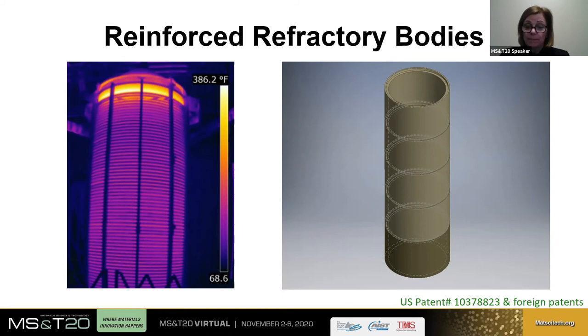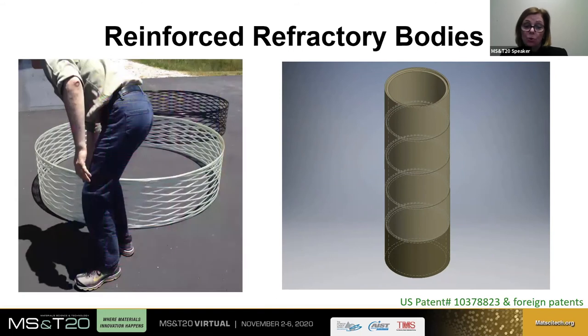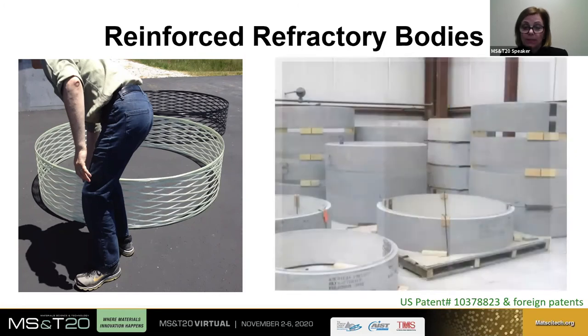In this example, we are inserting a fiber winding preform into a casting of refractory so that the winding is a component within the refractory wall itself. This system has been highly successful in the field. This is a balance of a number of input criteria and parameters, including but not limited to the type of fiber to wind, hoop stress at operational temperatures, the type of wind, and the refractory castable in use considerations.